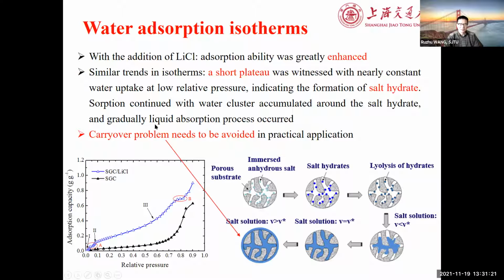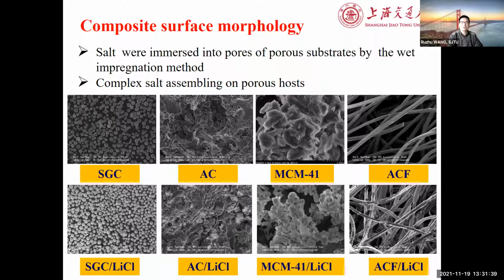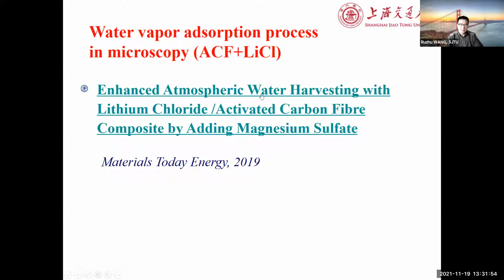And also we could use some process to prevent the carryover problem of the liquid, the leakage, and keep the liquid inside. This could be controlled by a thermal process. This shows the surface morphology for different kinds of adsorbent, enlarged under the microscope, even using some activated carbon fiber with lithium chloride.